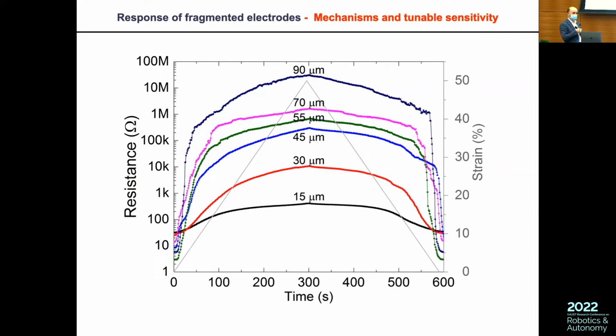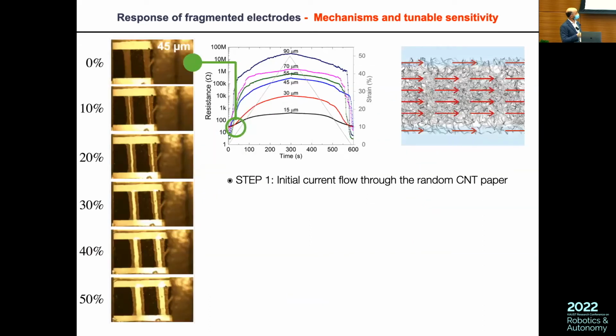Okay, so this is a super highly piezoresistive film, but of course, you can explain the mechanism based on the different steps of separation of the CNT paper. That means at the beginning, when the strain is low, you have a direct conduction through the CNT paper because, of course, all the CNTs are bridging together.